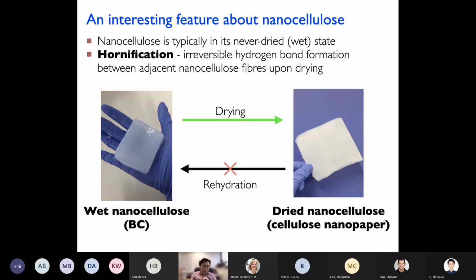So you have wet nanocellulose. In this case, we're using bacterial cellulose as a model, but the same thing works for wood-derived cellulose microfibrils. You dry them, you get a piece of paper, a dried piece of nanocellulose. When you soak this nanocellulose paper back into water, it doesn't go back to this state. Instead, it will stay as this piece of paper for as long as you can observe. We have soaked papers like this in water for about a year now, and it still stays as paper.